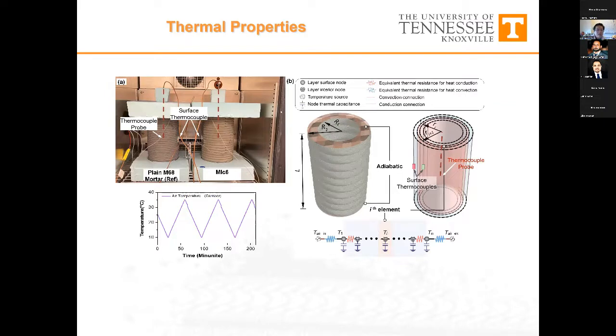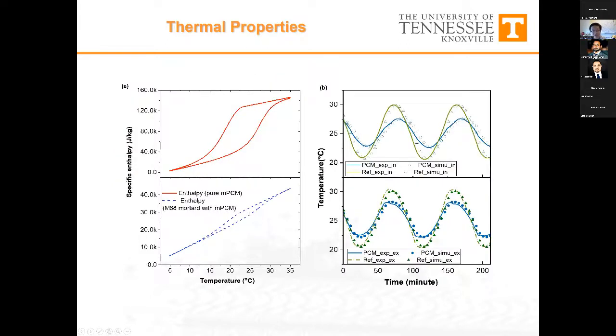So the way that we tested the performance is that we 3D printed a cylinder. That's a hollow cylinder that's using a reference mortar, which is commercially available. And then we 3D printed the same mortar mixture with 6% of microencapsulated PCM inside. And we placed them inside an environmental chamber, and we insulated at the top and bottom, and we inserted a thermal sensing probe at the very center to measure how the air temperature changes inside the cylinders. And then we basically cycle the cylinders in the environmental chamber to test this functionality.